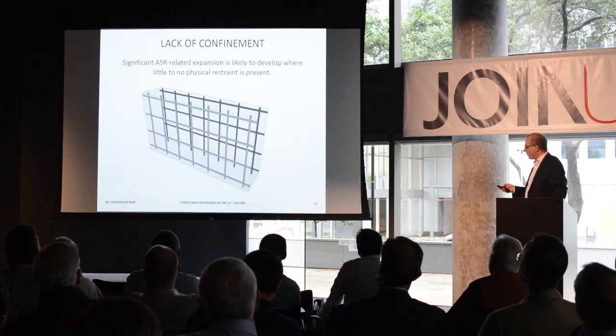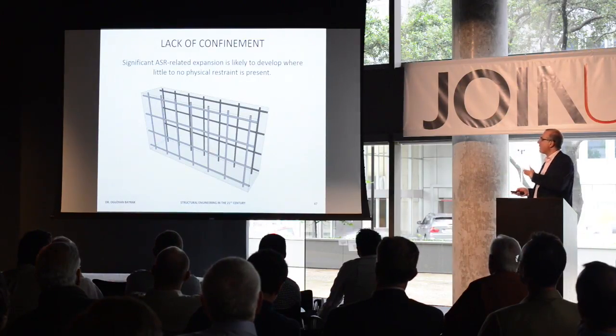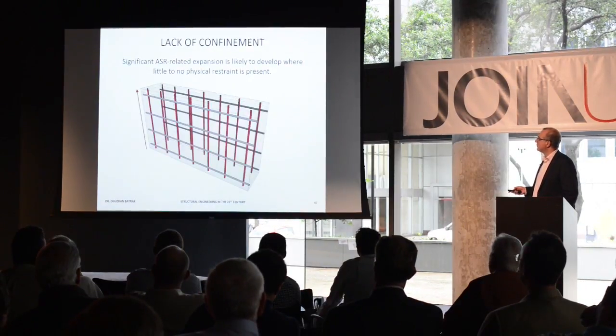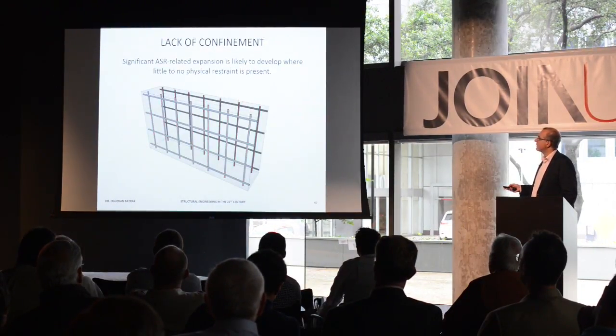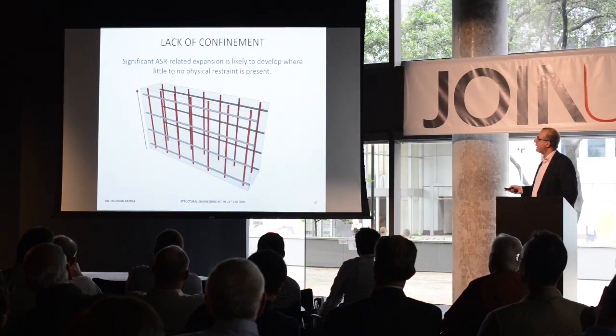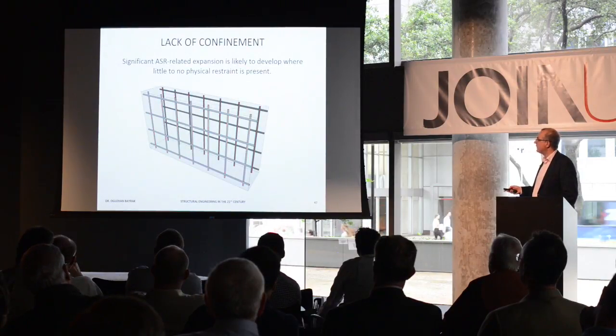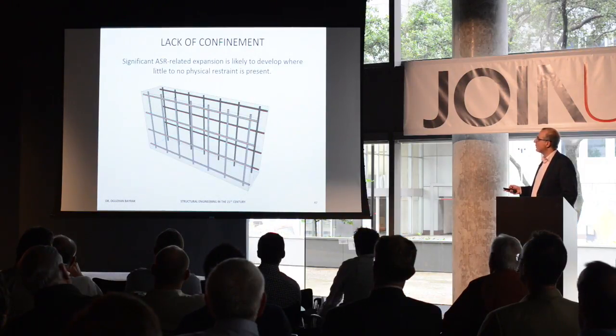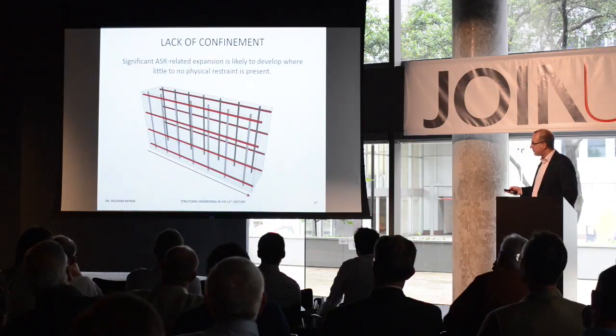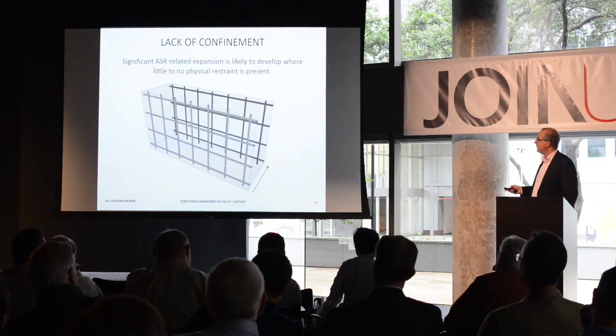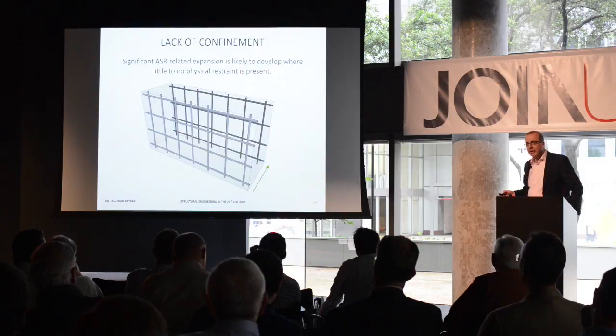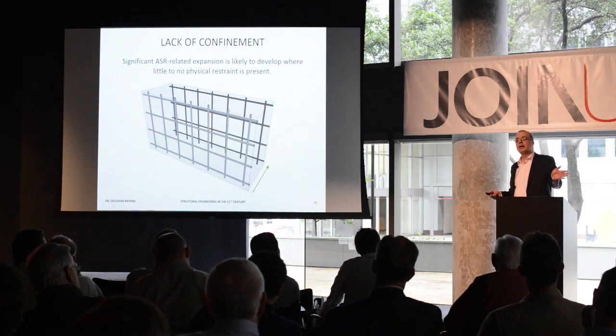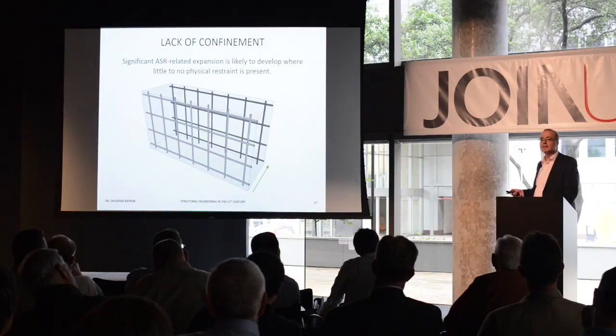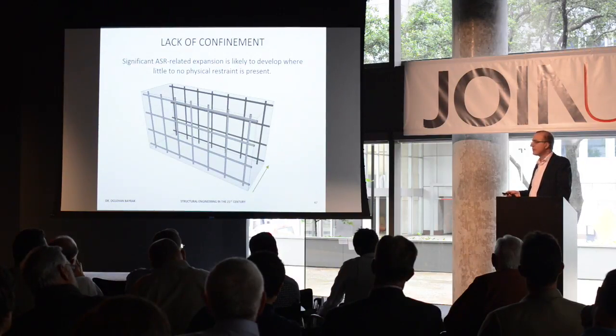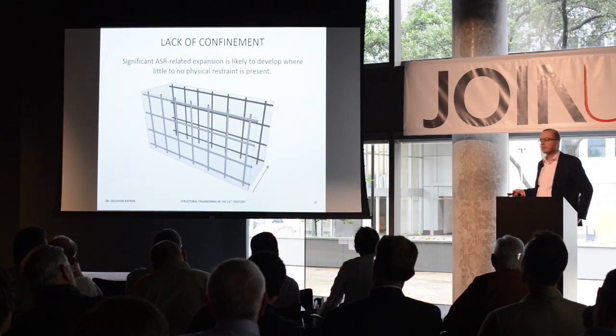In the nuclear power plant example that I was giving, there were a lot of structural walls with ASR damage. Certainly in the vertical direction, as ASR-affected concrete tries to expand, we have rebar that's restraining that expansion. The same argument applies in the horizontal direction, and expansion in that direction is restrained. But then there is the through-the-thickness direction, and as concrete tries to expand out of plane, there is nothing there to restrain it. It is for that reason that our current efforts at Ferguson Laboratory are focused on looking at the out-of-plane behavior of these structural walls.